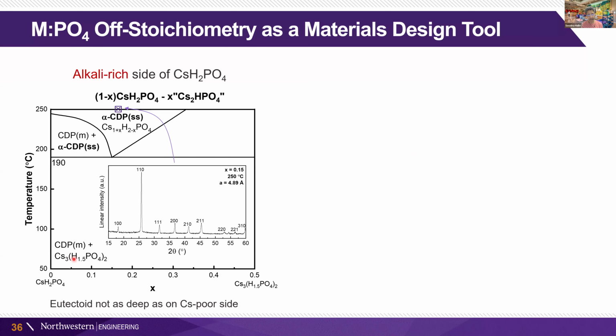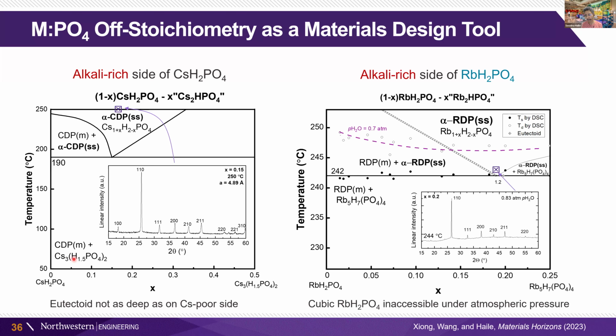We can use this off-stoichiometry actually as a material design tool now. We see that in addition to this alkali deficient cesium dihydrogen phosphate, not yet reported, we have an alkali rich side of the cesium dihydrogen phosphate. And similarly on rubidium dihydrogen phosphate, we can also observe an alkali rich side, which then in both cases decreases the transition from the monoclinic structure to directly the cubic phase or a mixture of cubic plus monoclinic.